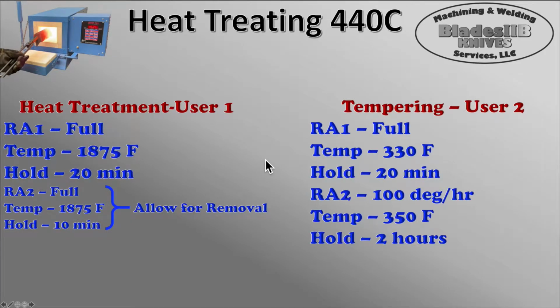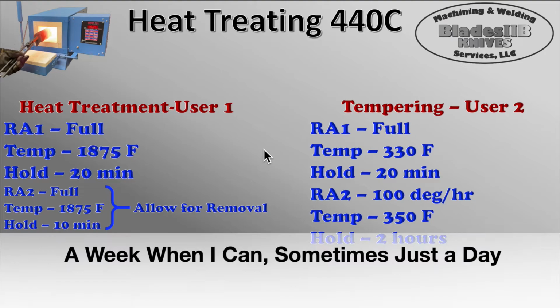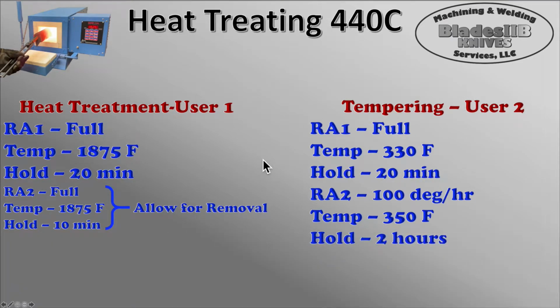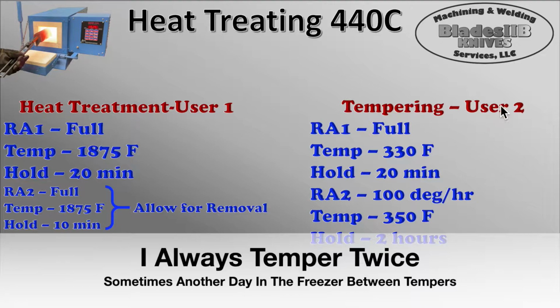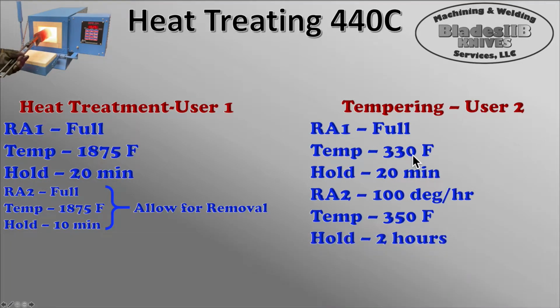After the knife is heat treated, I usually throw it in the freezer and let it sit for a few days, up to a week. I don't have a cryo, I don't have liquid nitrogen that I'm using to cool my blade, so I just use the freezer for a week and then I come back and temper that. So I have another program set up on my kiln for the tempering, and that one is going to be a full speed ramp up to initially 330 degrees Fahrenheit, and I'm going to hold it there for 20 minutes.